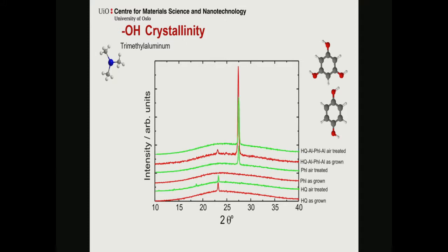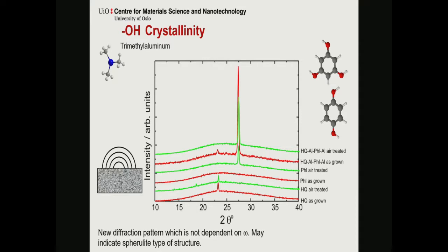And the diffraction peaks for the as-deposited and air-treated films were a bit different. If you did rocking curve analysis on this, we found that they had the same intensity overall, so this is not an orientation effect. We've not been able to decipher why they have the diffraction peaks they have. It's not due to the pure ligands themselves, and there are so few to look for.